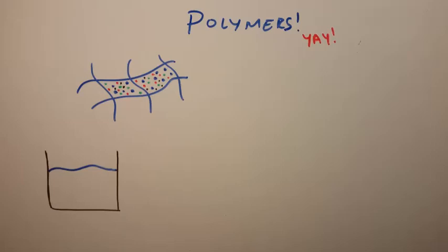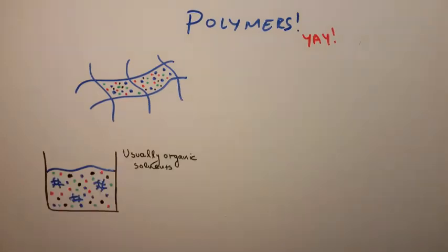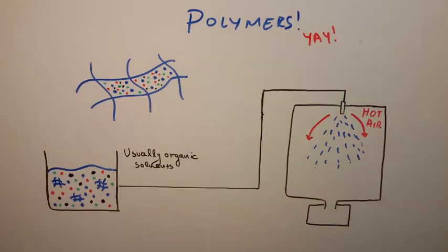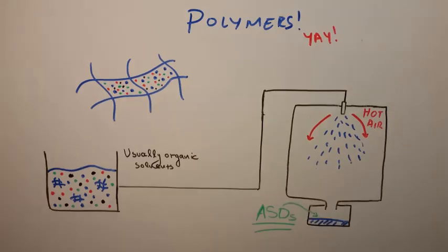The basic principle is that polymers and drug molecules are dissolved in a common solvent. The solution is then sprayed in a chamber with a simultaneous entrance of hot air. This causes the solvent to evaporate rapidly, causing material to be frozen in the amorphous solid dispersion state in the form of really fine powder that can be turned into tablets or capsules.